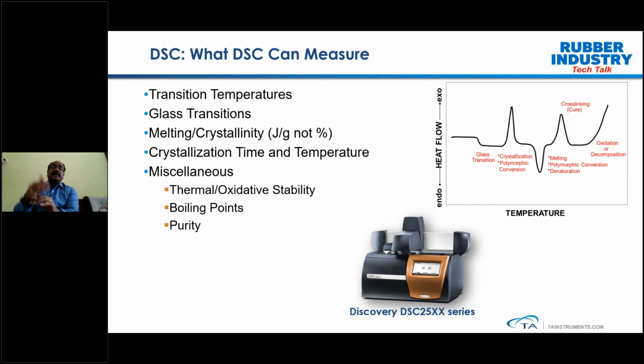So what you can see here is, if you look at the typical thermograms, we classify that whenever a sample undergoes any endothermic or exothermic activity, we can see that as a shift in the heat flow. So in this case, when the sample undergoes glass transition temperature, it is observed as an endothermic step. In case of crystallization, the curve goes in the exothermic direction. So we see an exothermic peak, and if it's a melting, you can see an endothermic peak.